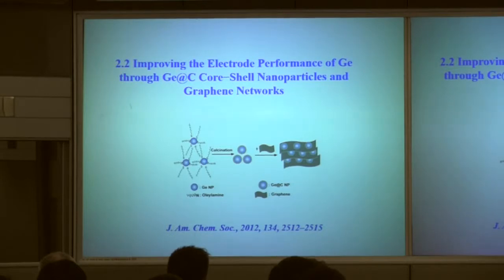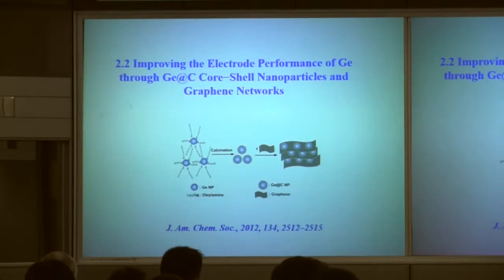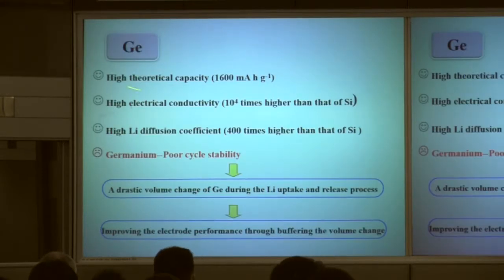We also made other composite materials. For example, silicon is also a very famous electrode material. Now, some silicon nanowire is used for lithium-ion battery. Besides silicon, germanium is also a very good electrode material, you see. But here is the advantage of germanium: high theoretical capacity, 1,600, is very high. But the weakness is very poor cycle stability because the structure is not so stable.